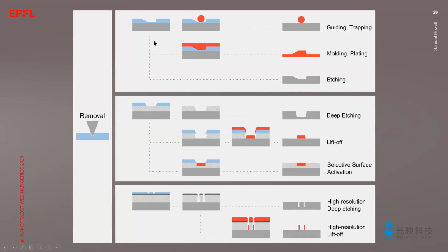For a single layer, patterns directly written into PPA can be used for writing traps or precisely tailored 3D landscapes for assembly of nanoparticles. And it has also been shown that the patterns can be directly used for molding or plating to create masters for nanoimprint lithography. And the pattern can also be directly etched into, for example, silicon oxide. However, PPA has a limited etch resistance, and due to the conical shape of the tip, it's only allowed to create shallow patterns with thermal scanning probe lithography. Therefore, in order to create deeper patterns, a second layer is typically added.